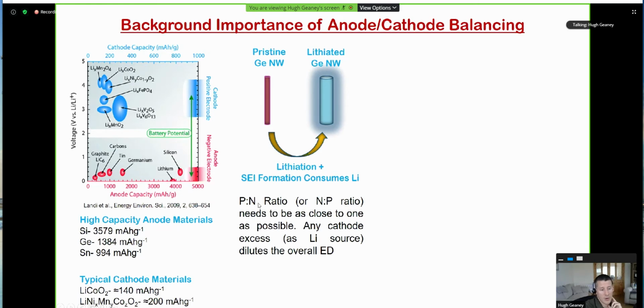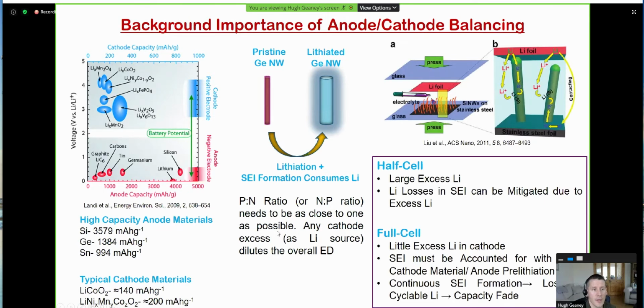So this PN ratio, or it's also called NP ratio, needs to be as close to 1 as possible. Essentially, if you have to introduce any excess capacity, you will do so by adding more cathode material, but there's a disproportionate penalty in terms of the weight to the cell to do that. So if you have to have excess lithium in there to accommodate any losses of lithium due to SEI, you'll have to bring in more cathode material, and you could completely dilute any of the energy density benefits of having a high capacity material in the first place on the anode.